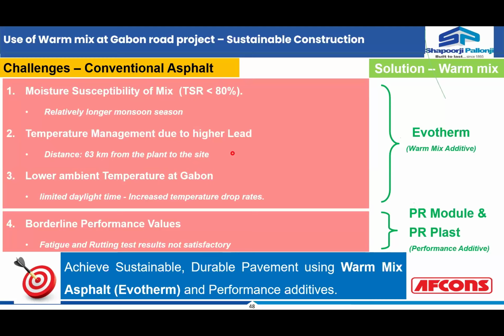And then the temperature management due to higher lead time. If your lead time is more, and you want to maintain the production, laying and rolling temperature, it's always a challenge in the case of hot mix asphalt, and you burn the asphalt in order to meet such challenges. So those things can be avoided if you are using a warm mix asphalt.